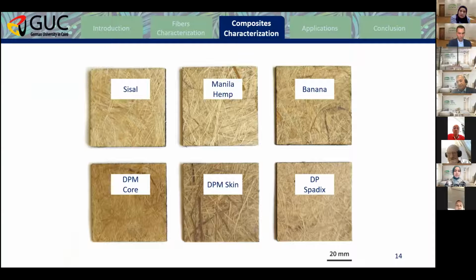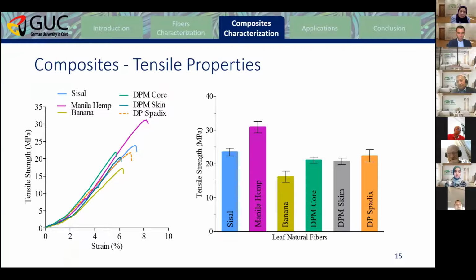all the fibers. Moving on to the tensile properties of the composites, it was found that manila hemp composite had the highest tensile strength compared to the other fibers, followed by date palm spadix, date palm midrib, and the sisal fibers. They were all within the same range, and there was no significant difference between their values. And finally, the banana fibers.